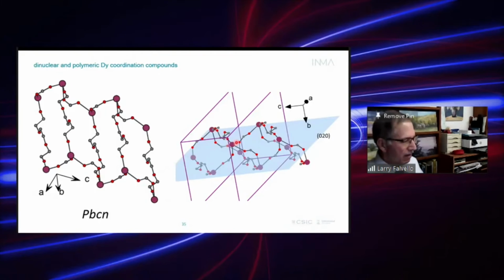And it turns out that symmetry then does not create new orientations. Other staircases will be parallel to this one. Right? So if the staircase is the basic unit we want to analyze, then we can do it with this orthorhombic crystal. And by the way, for an orthorhombic crystal, unlike triclinic, the principal axes of the susceptibility tensor are going to be along the A, B, and C axes of the conventional orthorhombic unit cell. So you only need 3 measurements.